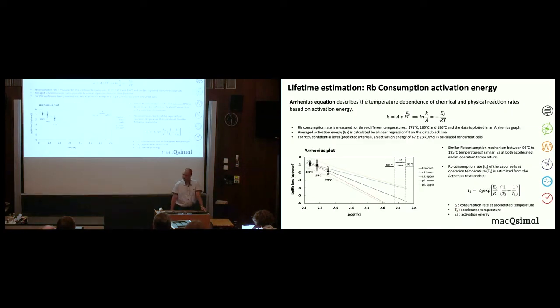A very common way is to use the Arrhenius equation, which describes the temperature dependence of many chemical and physical reaction rates based on activation energy. So what we did here, we took the rubidium consumption rate that we measured before, at 3 different temperatures. And we plotted here the logarithmic ratio in this Arrhenius plot, and then we can make an average. You can calculate.